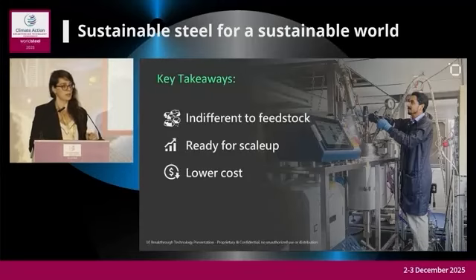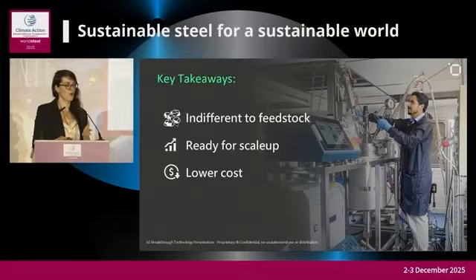So to summarize, we use low-value feedstock. It can be low-grade material, whether hematite, magnetite, goethite, and even wustite, and also waste products such as tailings and slag. From those materials, we convert to high-quality iron metal, and with a scalable and relatively practical process, we can change how we think and approach raw material in the industry.